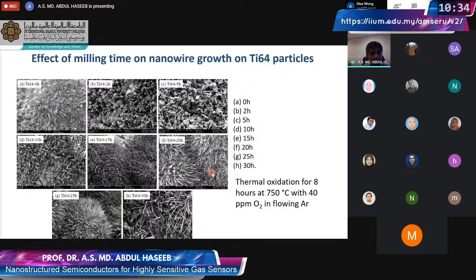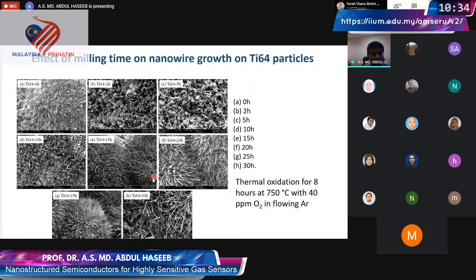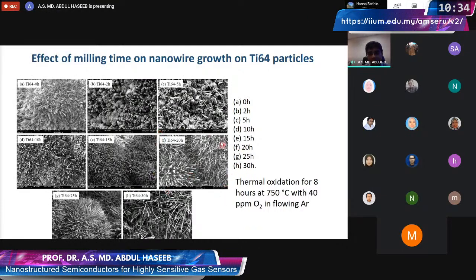And this is a demonstration of how effective stress is. As you see here, this is 0-hour ball milling, which means that the ball milling was not done at all. Then we increased the ball milling time from 2 to 30 hours. And we see that at longer ball milling hours, we grow quite nice, impressive nanowires on each of those particles. We tended to use the 20-hour milling condition, because if you go longer than this, you increase the power consumption. In our experience, that gave good enough coverage and amount of nanowires.